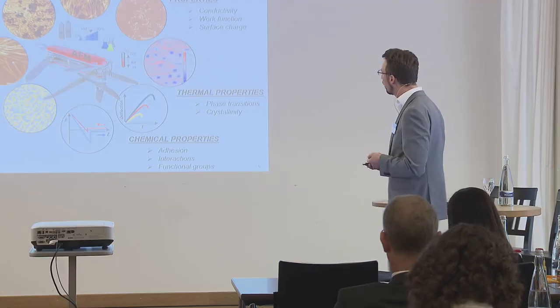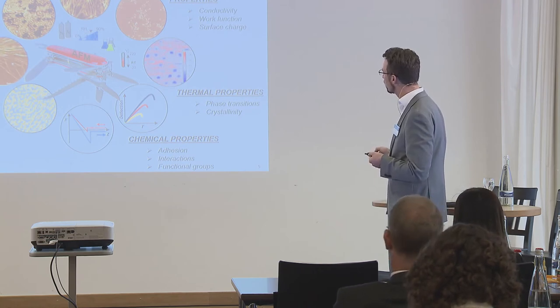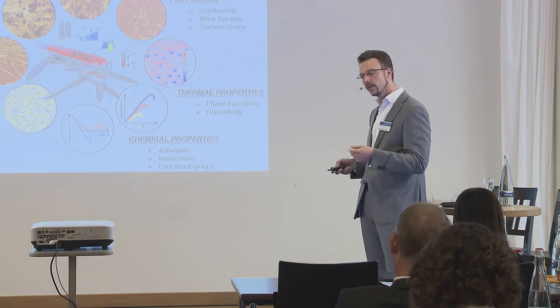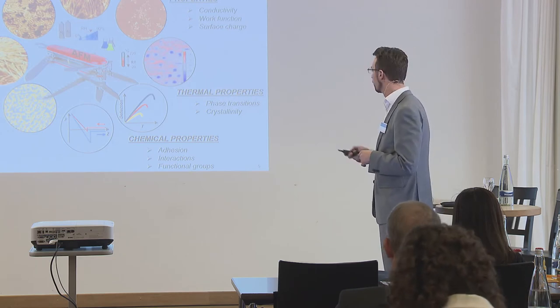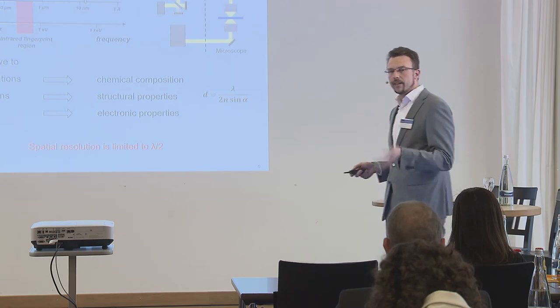A technique which came up just a few years ago is nanomechanical measurements. Here we do single force spectroscopy in each pixel of the image, really indenting our material. From these force distance curves, we can calculate the elasticity or hardness of our sample. But all the methods shown here lack or are missing something. We don't have chemical sensitivity. We almost never know what we are looking at. We have nice resolution, but we can only indirectly say something about the chemistry of our sample surface.